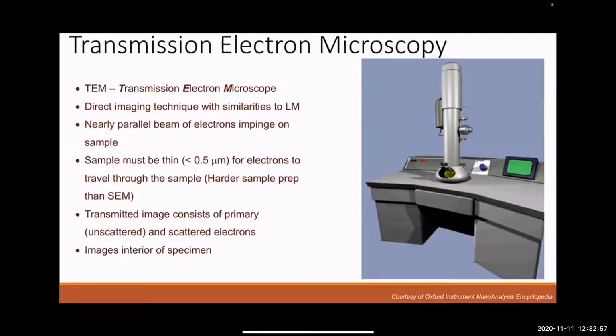So sample prep is an issue, and I'm not really talking about it today, but I'll just give you the quick idea. If you've got a polymer or a biological material like cells, you'll embed it in a polymer, and then you'll take very, very thin slices with what's called an ultramicrotome, which consists of a diamond or a glass knife, and you're just shaving off very, very thin layers of material. If you're a geologist or a semiconductor researcher with much harder material, you may be mechanically polishing it down and then following that up with some sort of ion etching to etch through your material.